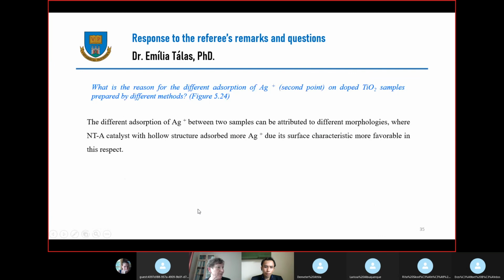And page 69, that's a question: what is the reason for the different adsorption of silver ion on doped TiO2 samples prepared by different methods? Yeah, the different adsorption of the silver ion in the ICP measurement between two samples can be attributed to the different morphology, where the NTA catalyst with the hollow structure could adsorb silver compared with the non-hollow structure. So it's due to the surface characteristic of the hollow structure, favorable in this respect.